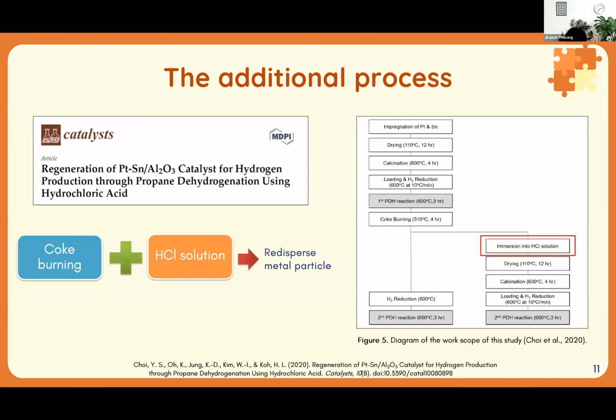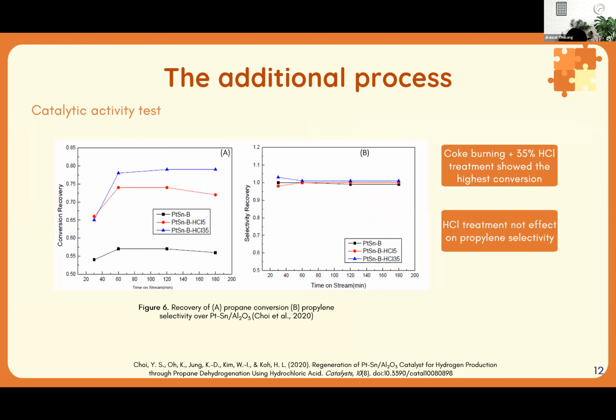For the next development in 2020, they used halide solution after the coke burning process. It can cause oxychlorination to redisperse the metal particles. This method is shown in figure 5. The conversion recovery shown in this picture demonstrates that secondary regeneration with HCl treatment gave higher conversion recovery than only coke burning, and figure B shows no significant change in selectivity recovery for the three catalysts.